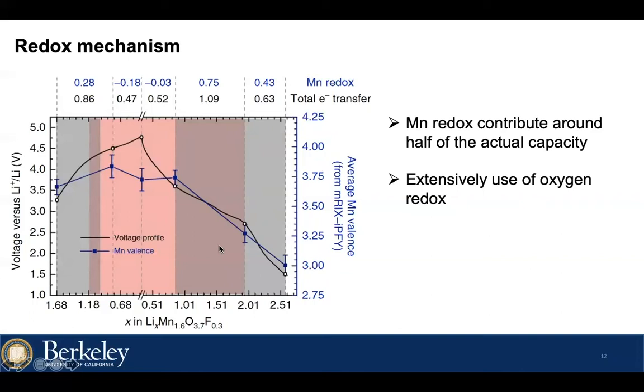Now, combining these two spectra that characterize both manganese and oxygen redox, we are able to draw this figure to show which redox contributes to each region of the charge and discharge process. The blue curve is the manganese valence change. The manganese was oxidized first during charge and got a little bit reduced at the top of charge. This is mainly due to the irreversible oxygen loss happening on the surface at high voltage. And during discharge, the manganese valence stays constant first, and then gets reduced almost linearly with the lithium insertion.